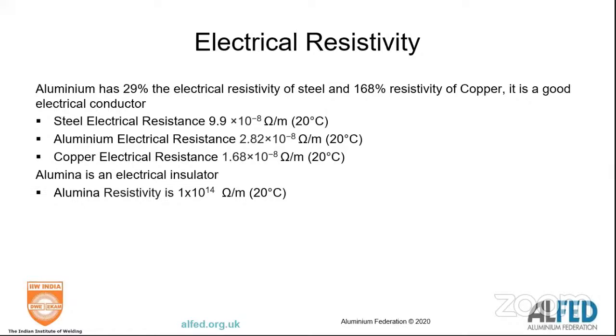Pause a minute and let's look at electricity. Aluminium's actually quite a good electrical conductor, and its resistivity is about a third that of steel, roughly 1.5 times that of copper. So a poorer conductor than copper, but a really good conductor compared to steel. So in terms of welding, we consider it to be a very good electrical conductor.